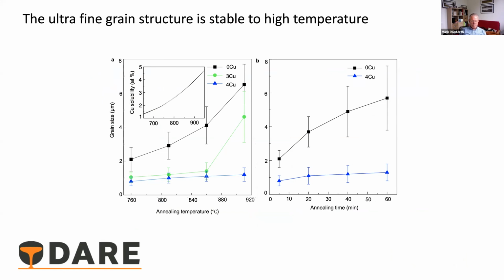And you can see the baseline material, if you start off with this 2 micron grain size, as you heat it up, it very rapidly grows, and you get very rapid growth even within this time frame. Whereas the 4% copper is really quite stable. The 1 micron grain size, which of course has a very strong driving force for grain growth, nevertheless stays stable even with an hour annealing at a high temperature of 900 or thereabouts.